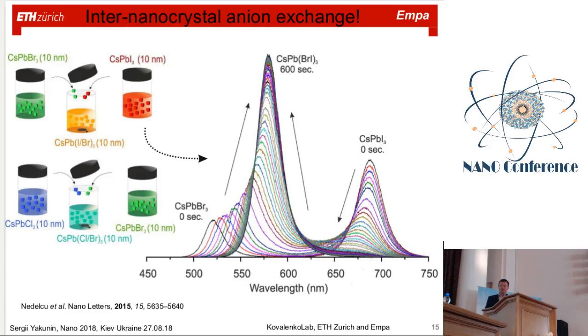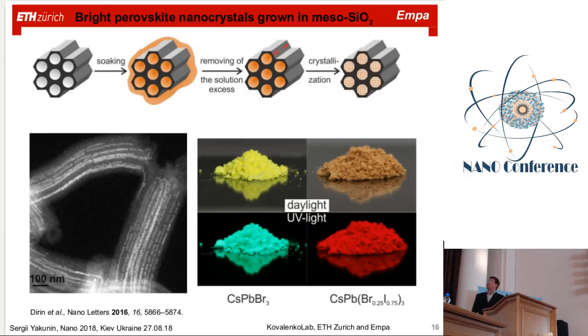It makes very big trouble for people who are trying to apply this material for solid state lighting, trying to combine this material in order to make very broad white light emission. So they would need to encapsulate these materials. And another interesting example of how we can play with this material is that we can put this perovskite nanocrystal inside mesoporous silica.